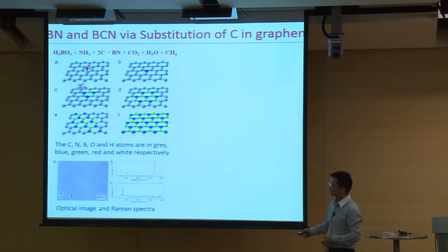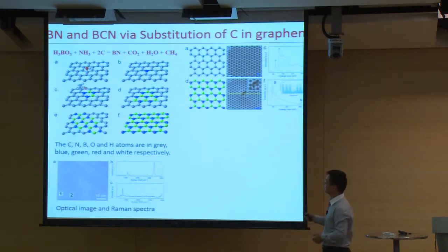And this is a partially converted boron nitride. What you can find is some areas of boron nitride and some areas of graphene. This is the Raman signature. And we also examined the quality of these materials. This is the CVD graphene before conversion, and this is the boron nitride after conversion. So the quality is reasonably good.